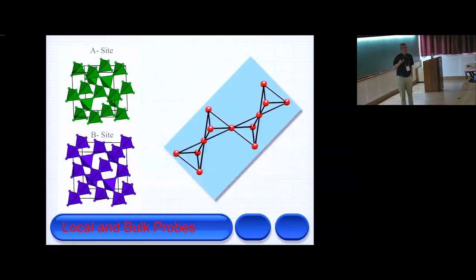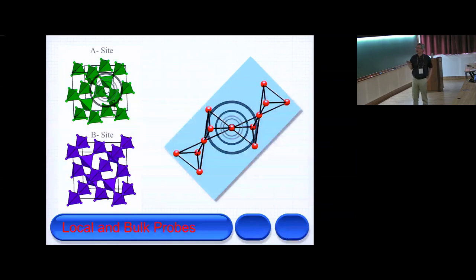So we also have local probes, as was alluded to. In this case, you could have NMR, where an element is your probe, really, and you measure some effects locally from that site. So when I show you some yttrium NMR in the future, we use NMR to probe the nucleus of this yttrium, and we look at its surroundings. But it's not long range, it's not the average bulk. You can actually start to see details.